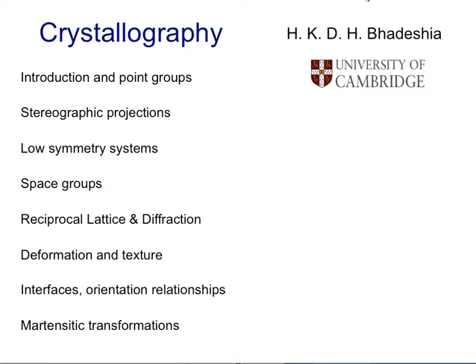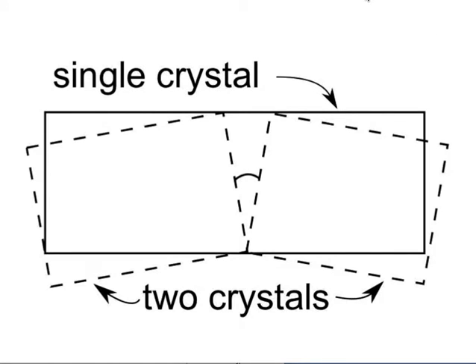So what we'll do is we'll start with a single crystal and create an interface. We'll slice it in half and create an interface. This is a simple kind of interface where we take a single crystal, cut it in half, and tilt the two halves by an angle theta with respect to each other. This is called a tilt boundary. Unfortunately, when I cut it and tilt, I'm left with a gap, right? You can see that here there is empty space, and we know that we don't have that inside our polycrystalline material.